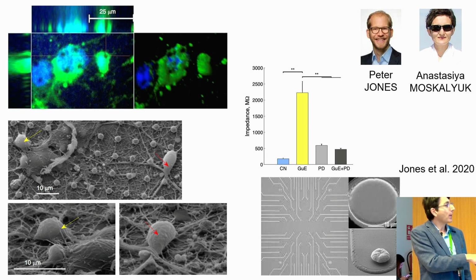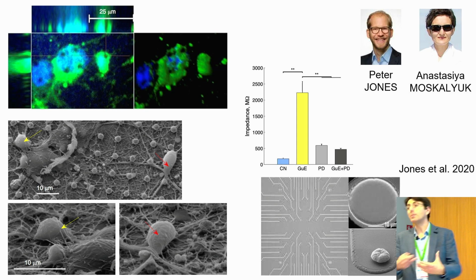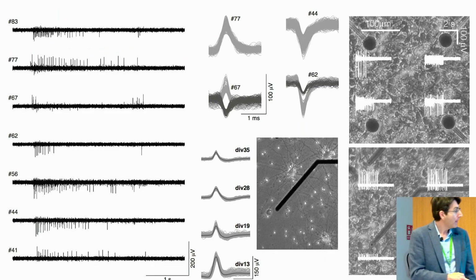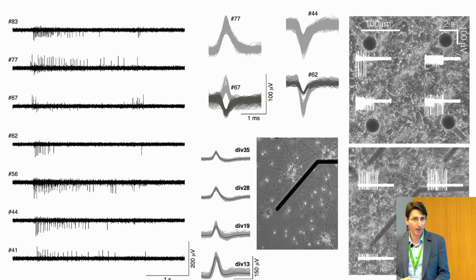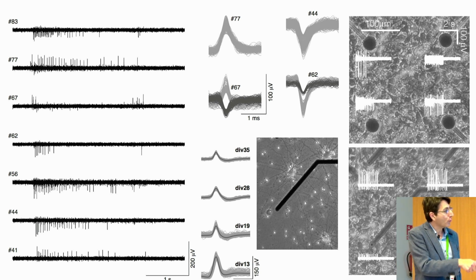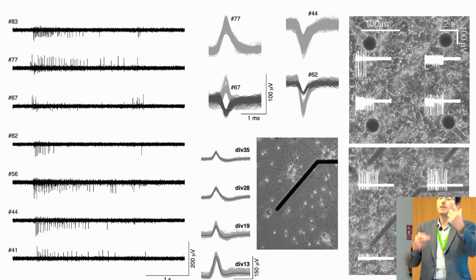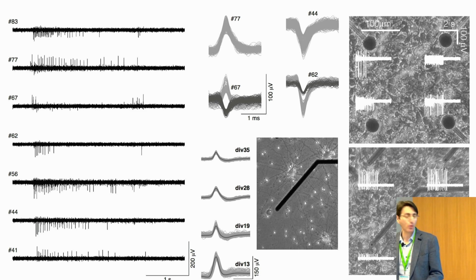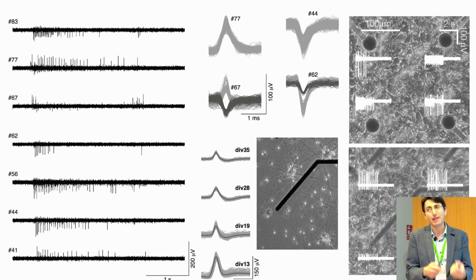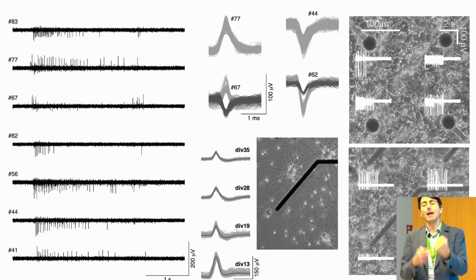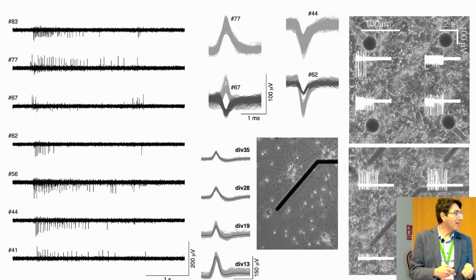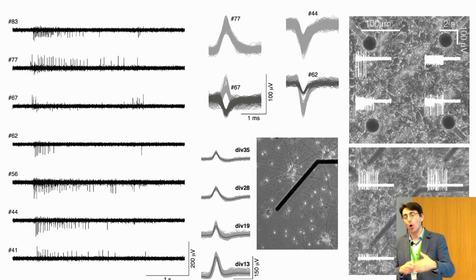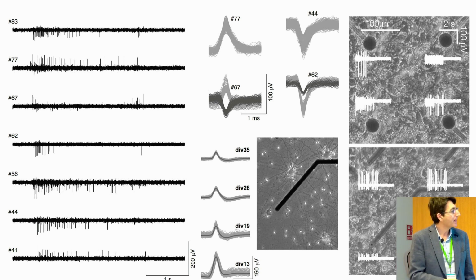So very high impedance can be restored to the level of conventional electrodes if you use PEDOT or PEDOT nanotubes. And what we found is that throughout the days, indeed, the number of electrodes that had positive deflections, I'm just going a bit fast here, compared to control electrodes was higher. The positive deflection could have several explanations, of course, but we thought that this could be an indication that indeed we were somehow approaching this configuration envisaged by Micha Spira of having an in-cell, almost quasi-intracellular coupling.